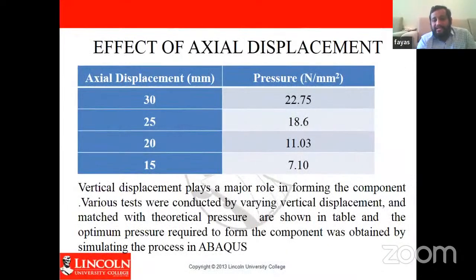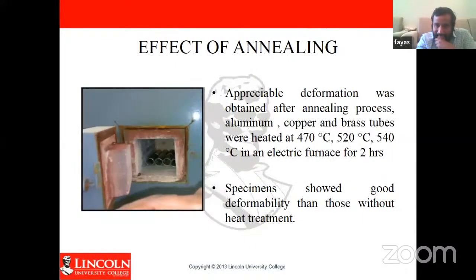So this is the axial displacement. We did it only for aluminum, because for aluminum we did four different pressures. Whenever the force decreases, pressure also decreases. And then annealing: we did annealing as noted in the literature of the paper, at 470, 520, 540 degrees Celsius. The specimen shows good deformability compared to without heat treatment.